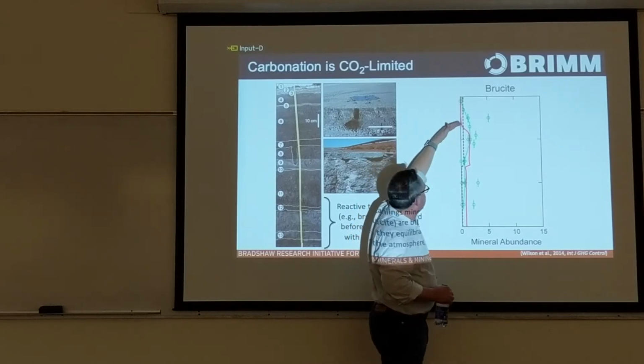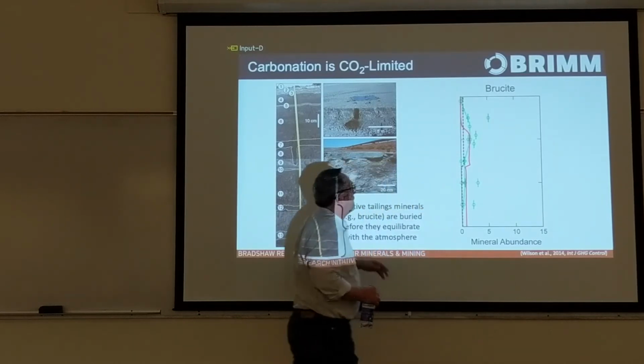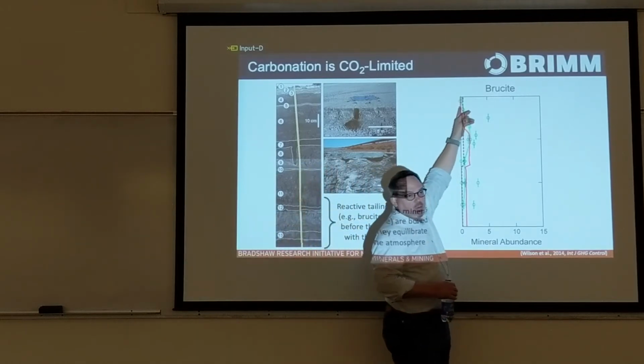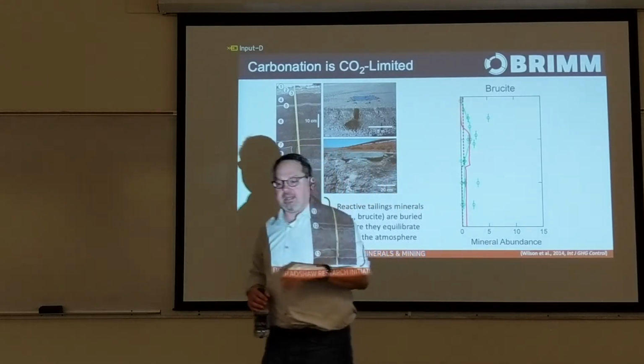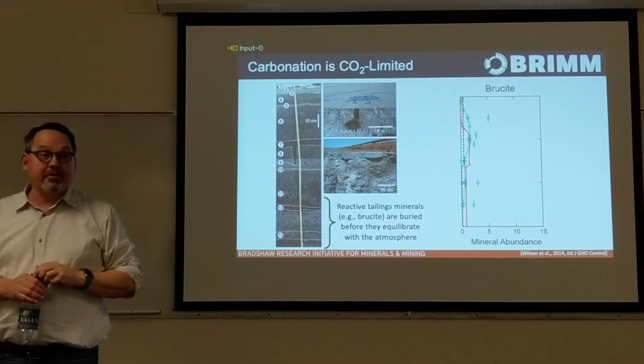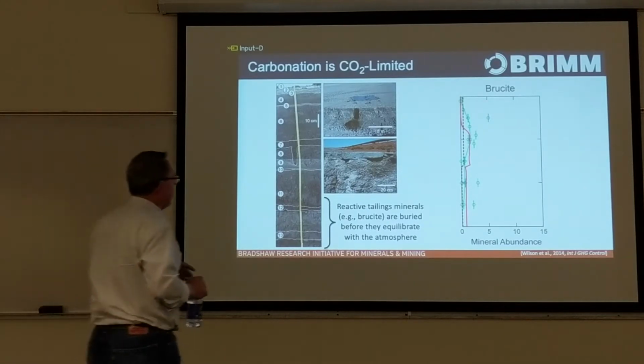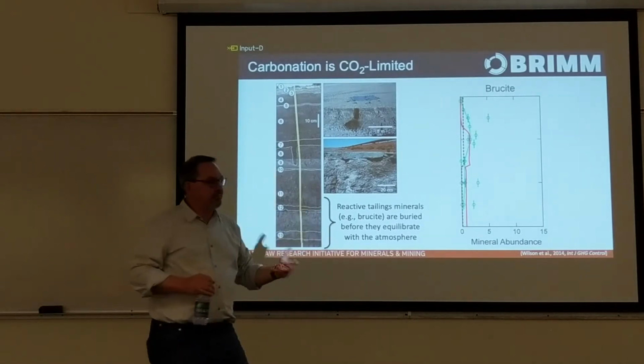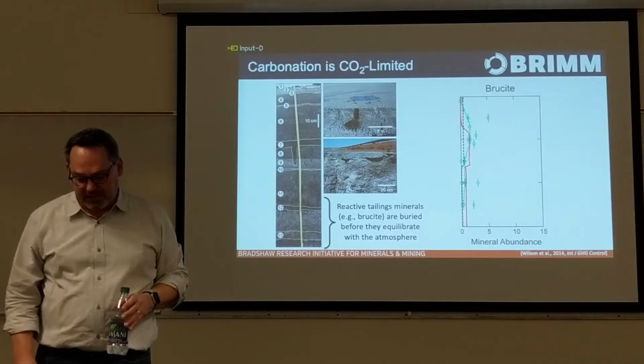This is a 1.5 meter depth. I lost the distance on this, but we see we have brucite content. It's gone at the surface. This is an old tailings flow, so brucite's been fully reacted at the surface, but we've buried a whole bunch of reactive minerals at depth. So we know that we've buried labile magnesium. We could have reacted these things further.